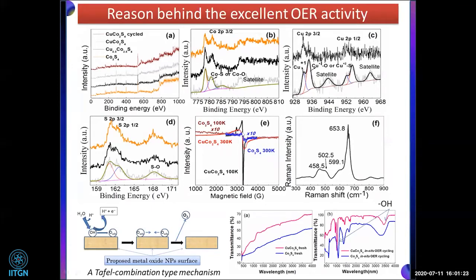And from the EPR spectra, what we can see is an asymmetric broad resonance. We have done it at room temperature as well as at 100 Kelvin. And one more thing here: the uncoupled cobalt 2 plus signal is absent in this one. So what it says is that in this copper cobalt sulfide, cobalt 2 plus is ferromagnetically coupled with other cobalt atoms, and mainly it is cobalt 3 plus, in high spin state, that is t2g4 eg2.